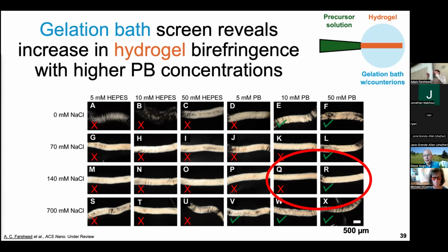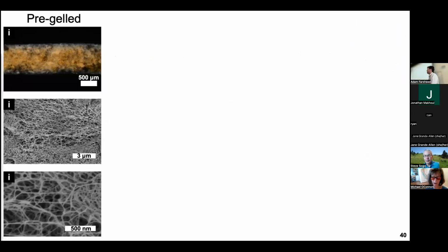And so now that we'd kind of qualitatively screened a bunch of gelation baths and a bunch of precursor solutions, we did a much bigger deep dive into this. So in all the left side, I'm going to have our pre-gelled solution, which again is from AIM-1. That's our negative control, where we're looking at the top, an image of polarized light microscopy. So there's maybe a little bit of brightness. And then at the bottom, we're looking at scanning electron microscopy. When you zoom in on that structure, there doesn't seem to be any sort of alignment.